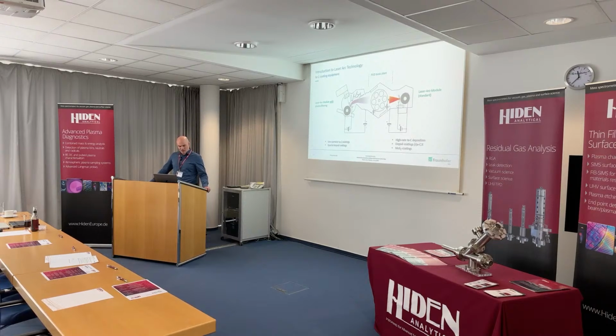This is one problem we had, and we had to overcome this, and how we did this I'll show you later. And of course, special doped coatings we can also put in through the filter, so we can evaporate and see differences by the filtering, because our filter is usually ion energy selective, and so there are also effects if we evaporate doped cathodes in the system. And on the other hand, on the right side, we can do all kinds of coatings. What we also did is MoS2 coatings, which are working very well, and we got a much better adhesion than the sputtered films. They are available on the market, and maybe there is an option for applications, but it's a complicated process, and I don't know if someone in the industry wants to do this, except there is this advantage of these kinds of films, that it's making the cost valuable.